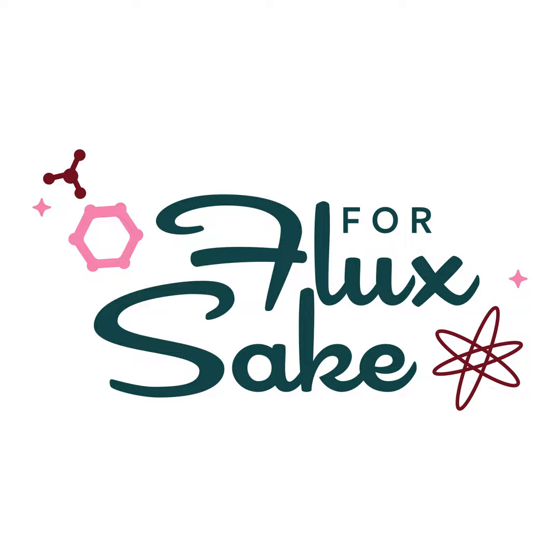You might have to go back and sort of polish that down, because you may get a lot of alumina granules sticking to it. Yeah, I've had to do that. Even trying to scrub it off, sometimes it'll stay on there. So getting some wet dry sandpaper will take that off, or a blowtorch. But you have to be even more careful, because if the alumina wash touches your glazes, they can get all nasty. Yes, I have messed up some pieces with the little drip lips.